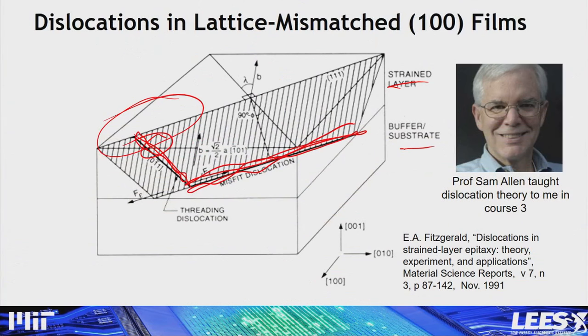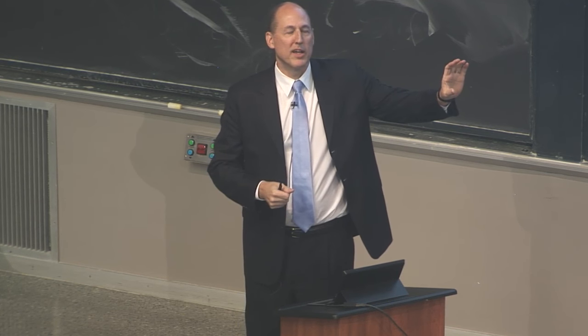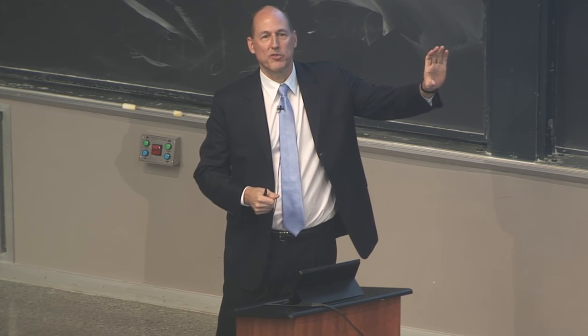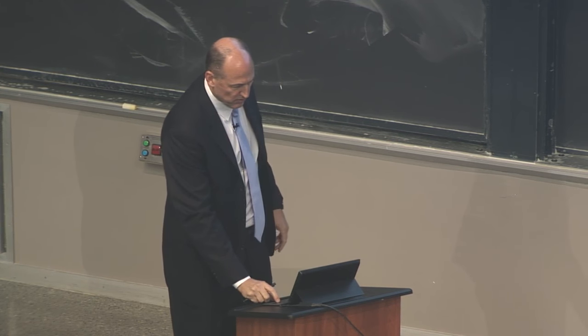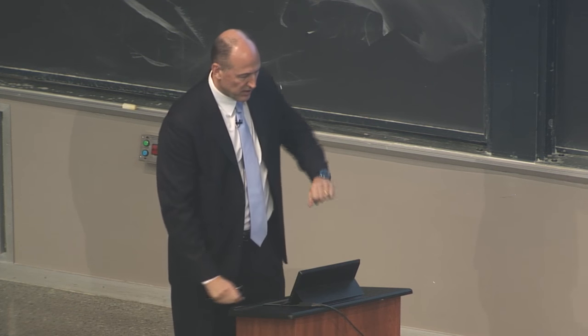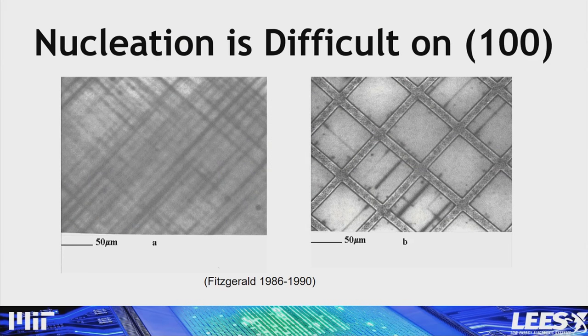At the time, Sam Allen, a professor who retired a little while ago in materials science, taught me the basics of dislocation theory, which, in the semiconductor field where nobody knew it, ended up being my key added value in trying to figure out this problem, right? So it's an interesting collection of little threads that led to something important. The key thing I was able to do in grad school was to determine that you can actually manage these defects when they come in. People thought, well, if you deposit a material with too big a lattice mismatch, it ends up being lousy and you just can't use it, right?